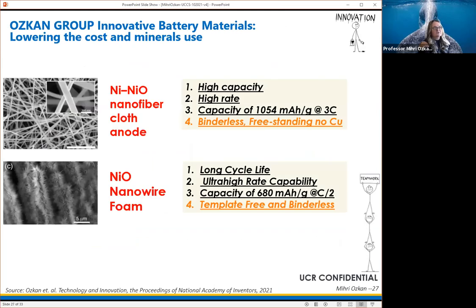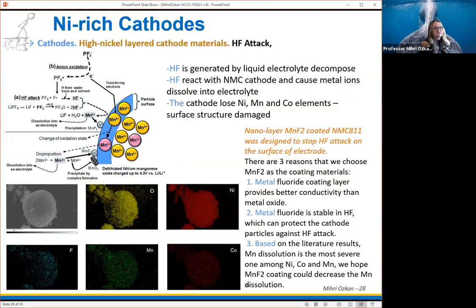And we have patents on those as well. And because of this, again, potential mineral shortages that we are expecting, we wanted to go to the elimination method and not use some of the components that are part of the current traditional batteries, for example, without copper, without binder. That's how we developed these two technologies, using nickel oxide nanofiber cloth anodes, which are binderless and freestanding without copper, and nickel oxide nanowire foam, again template free and binderless. So these are some of the technologies we used.